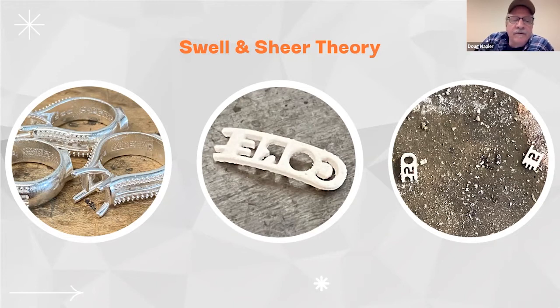We could have got by with half of that thickness. But you can see, this was before the metal got in there. This was just from the burnout process. So it's actually looking at some of these areas and it's shearing off pieces of investment that are just kind of weak areas and unsupported. And especially if you've got thicker areas, that's going to be intensified even that much more.